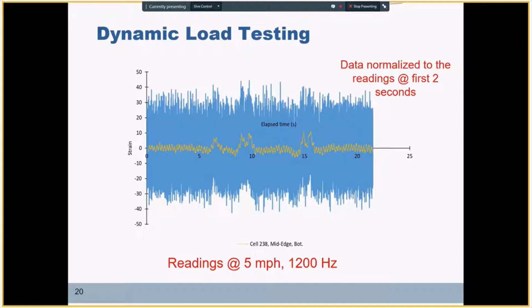Strain gauges were also embedded in these concrete sections at different locations, at corner and mid-edge, top and bottom of the pavement, to monitor the response of the pavement to dynamic loading. The loading on these sections is done by a 5-axle, 18-wheel truck with a weight of 80 kips. These are a sample of the data for the dynamic load testing.